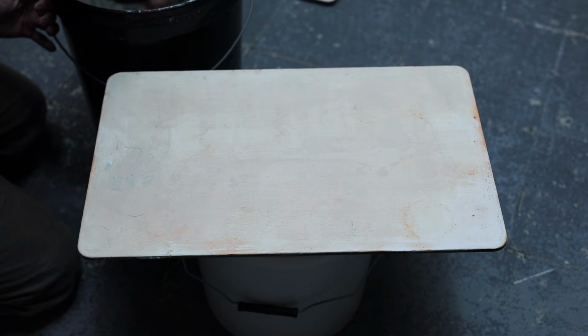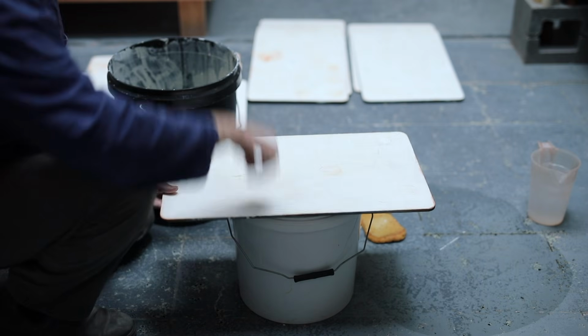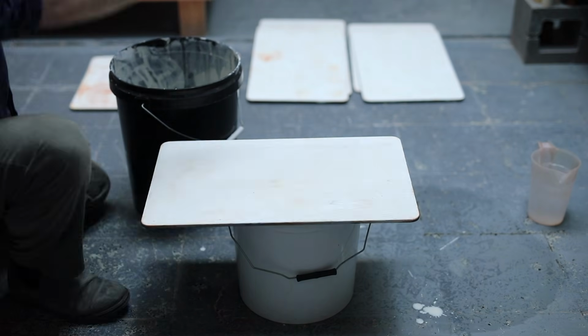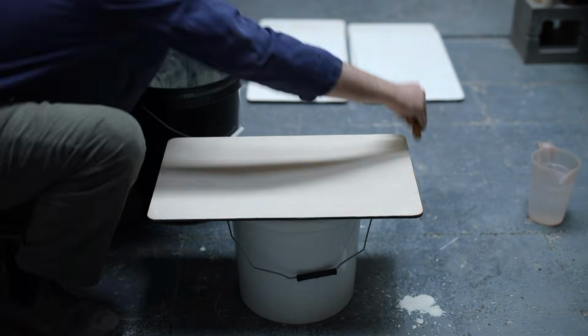These are then packed into the kiln, and after packing the kiln, I'll preheat it for a little bit, just to make sure all the kiln shelves are properly dried out, as these types of shelves can explode if they're fired when still damp, leading to absolutely disastrous results.